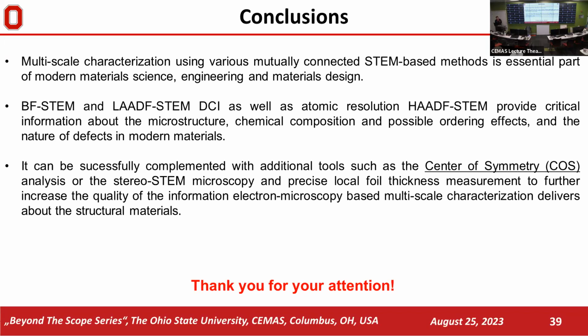If the samples are thicker, we mostly work with bright field, because it's easier to just use the transmitted beam and adjust the convergence angle to get the transmitted beam into bright field, and then the diffracted beams are shielded out. So it's easier, and if the sample is thicker, they're not such big issues.